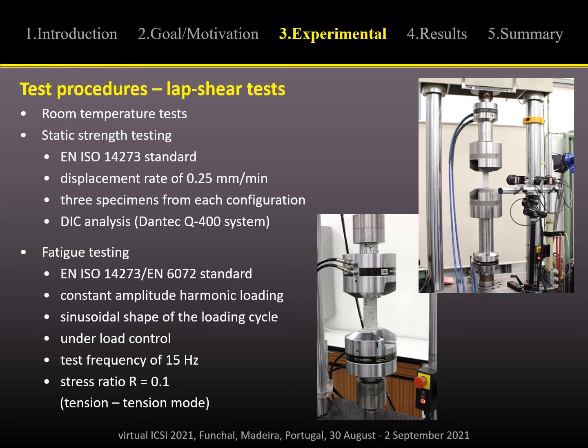Regarding the test methods, all tests were done at room temperature. The lap shear strength test was done according to European ISO standard 14273 under a displacement rate of 0.25 mm per minute. Always 3 specimens from each configuration were tested, and DIC digital image correlation analysis using a Dantec system was used for strain distribution evaluation. The lap shear fatigue testing was done according to European standards 14273 and 6072, with constant amplitude loading with a sinusoidal shape of the loading cycle, load control at a test frequency of 15 Hz and a stress ratio of 0.1, so it means tension mode.